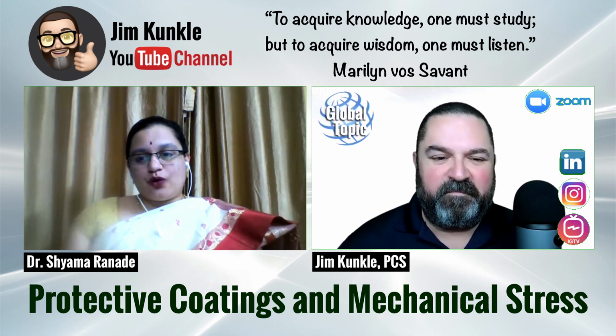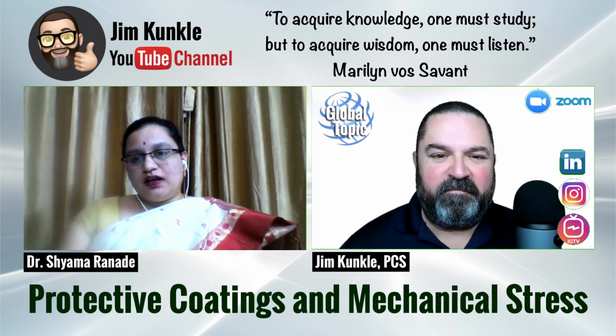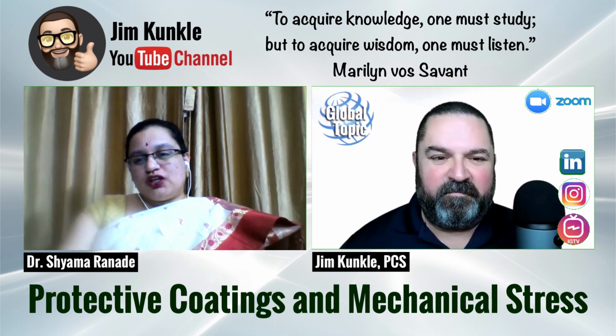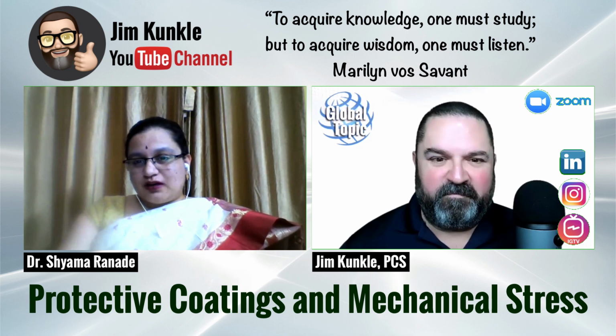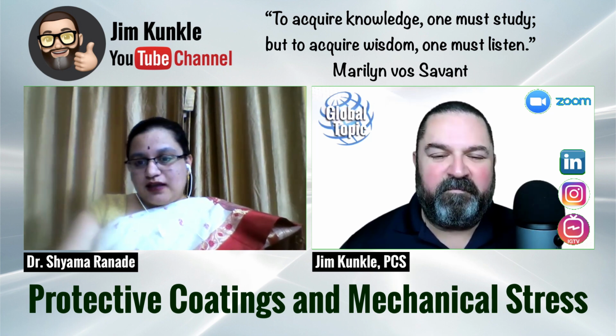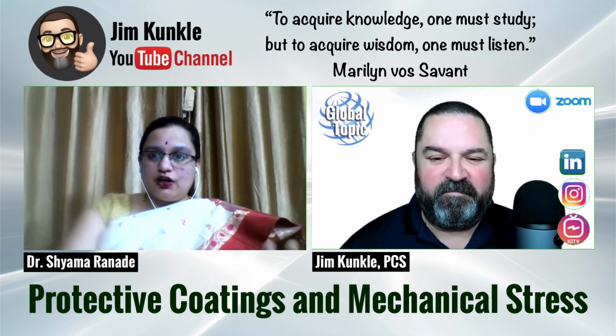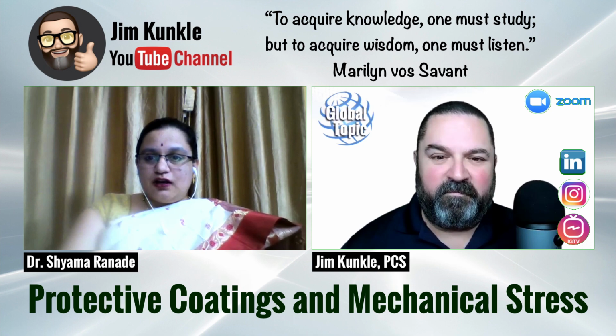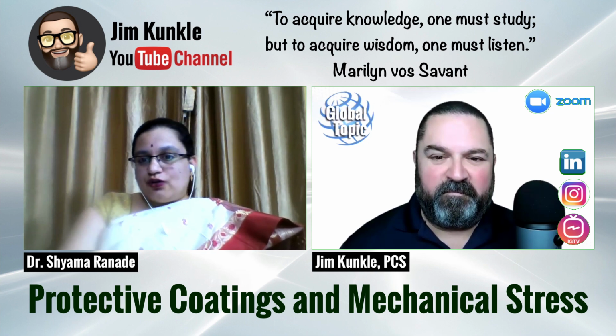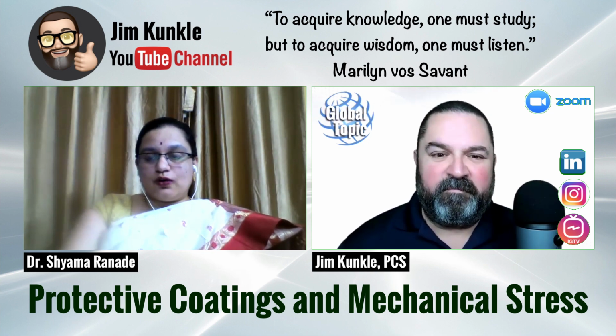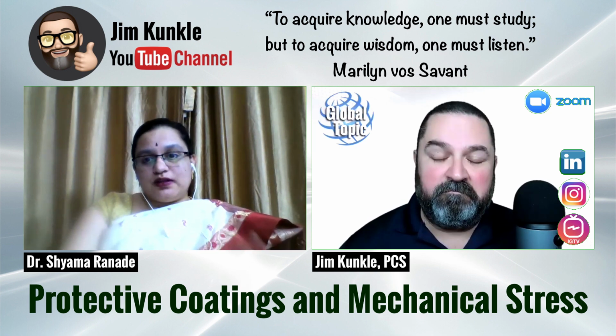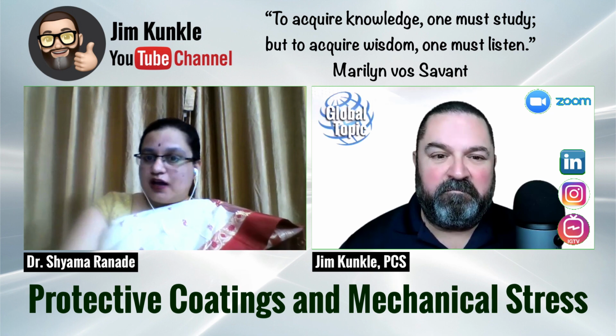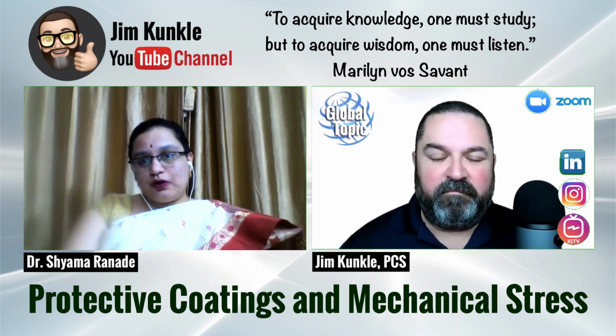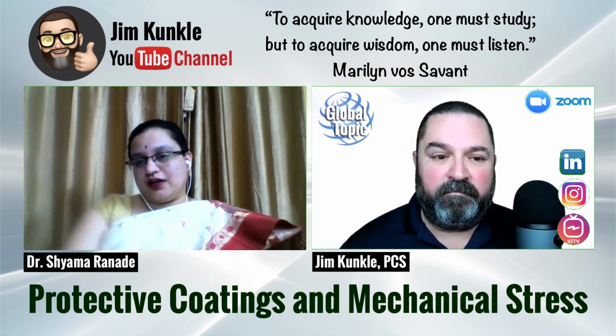There are three main problems that this causes. One is cathodic delamination, second is hydrogen embrittlement, and the third is a collection of hydrogen gas, which is said to lead to delamination of the coating, but there are studies that still debate that topic. And there's the other range, where you have a shielding coating that does not allow any CP currents to go through it. So even if you have a bit of water collection underneath, you do not have any protective currents for the pipeline. That's why you need a correct balance between CP and the coatings. You have to have either an optimum CP potential, or you choose a coating which matches the CP current as well as the application.